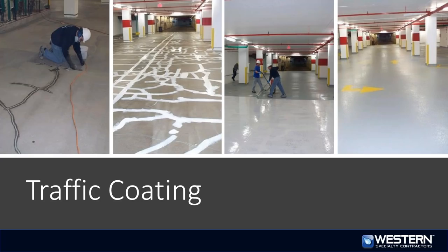This is a parking garage, and it runs through the scenario of typical repairs for what we would do for a coating. The picture on the left shows someone who has routed out the cracks already, and these have been sealed with a urethane sealant, primed and sealed. And then the second picture is once the cracks have been detailed. So the process for a urethane deck coating is what typically gets installed: you caulk the cracks, then you detail the cracks and all perimeters with a urethane base coat.